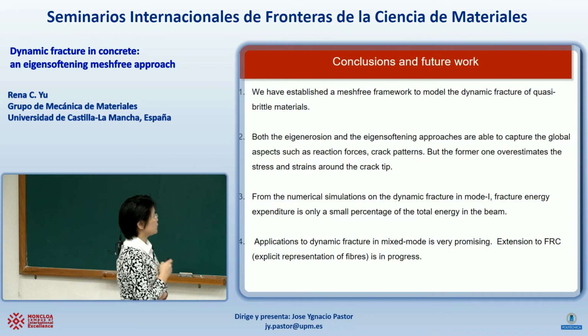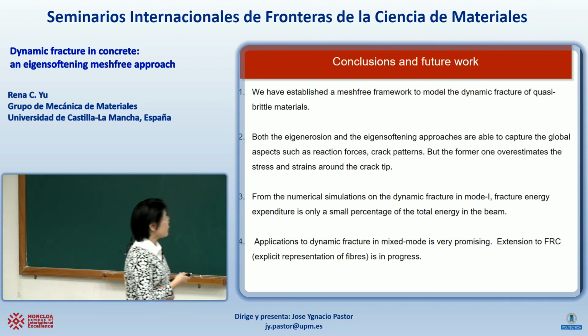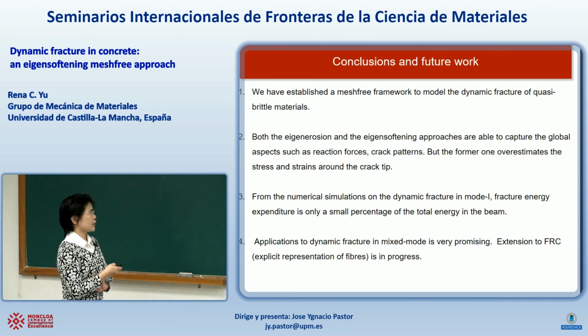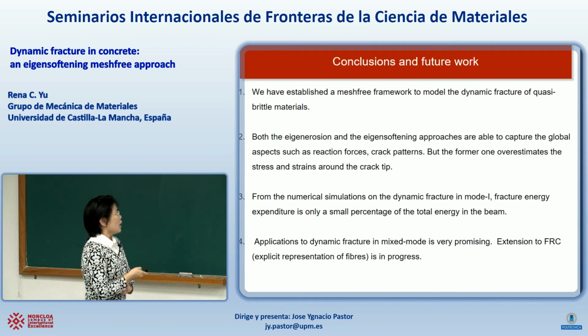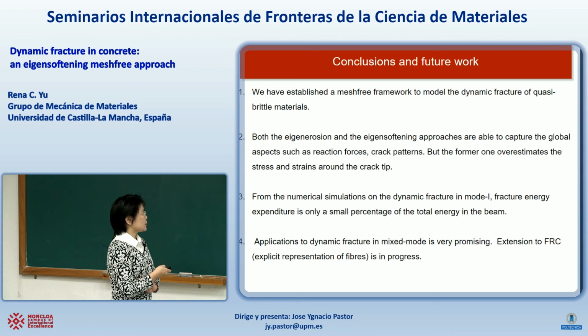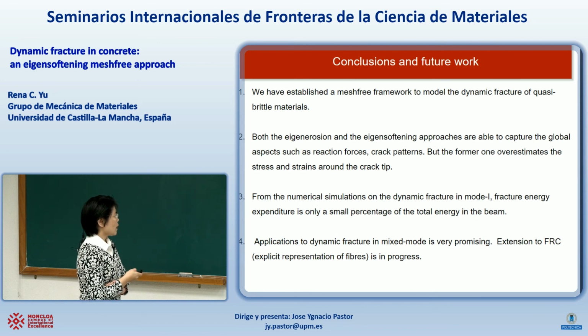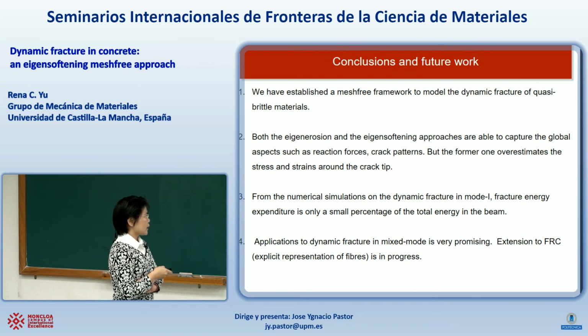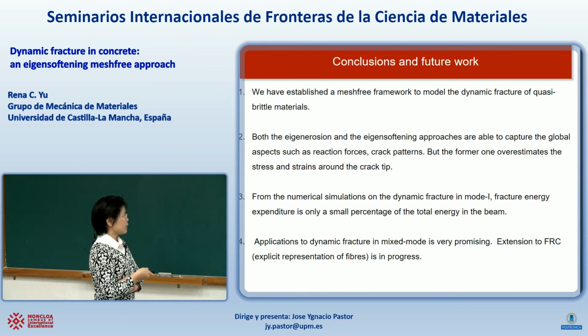So now I come to the conclusions. We have established a mesh-free framework to model dynamic fracture of concrete. Both approaches, eigenerosion and eigensoftening, capture the global effects like the reaction forces, and also the crack pattern. But the eigenerosion approach overestimates the stress and strains around the crack tip. And from the numerical simulations on dynamic fracture in mode 1, we see that the fracture energy expenditure is only a very small amount of the total energy in the beam.